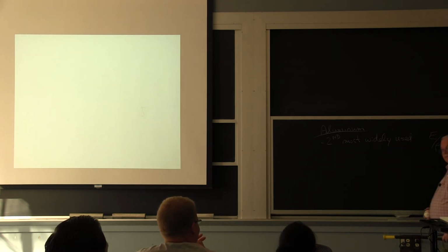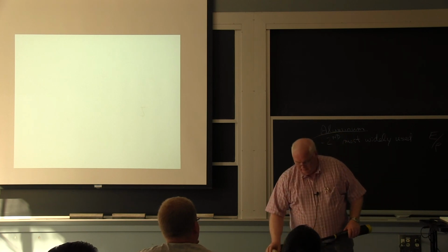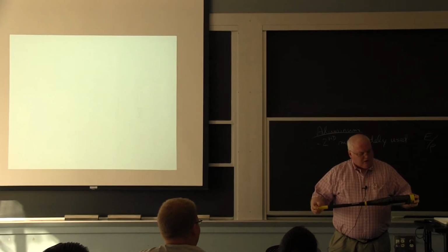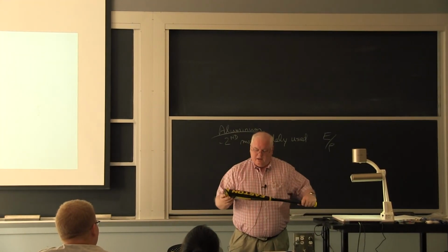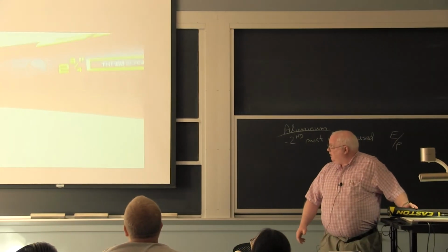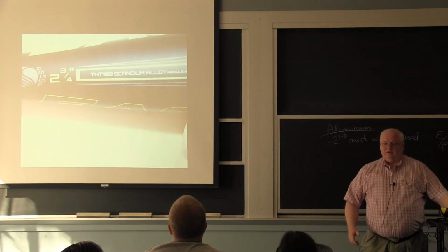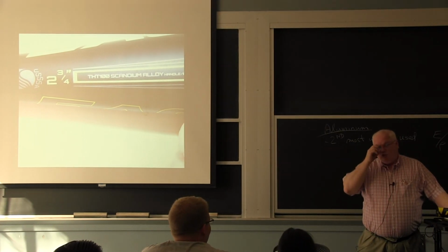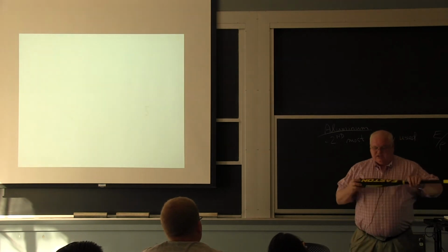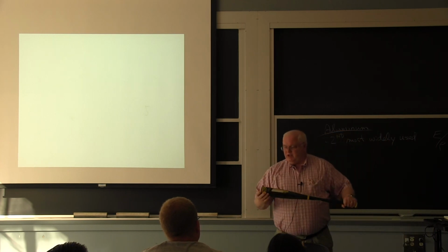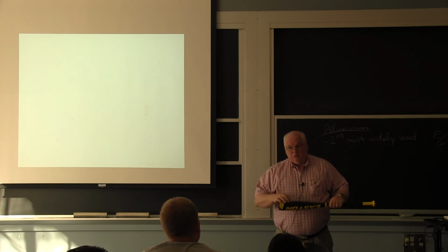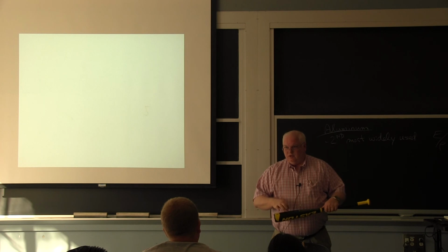Okay, so this is about the right time to just tell you the story. I paid $130 on Amazon for this. Typically, you might pay $300 for a bat. It's a THT108 scandium alloy. This is the world's largest use for scandium. We only make 2 tons of scandium a year. And the Soviets discovered, again, that scandium is a tremendous grain refiner. When they make these metal bats, they extrude them, and they have a relatively thin wall. This may have a 28 thousandths or so wall.